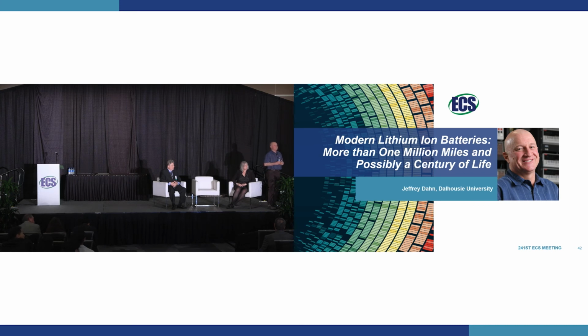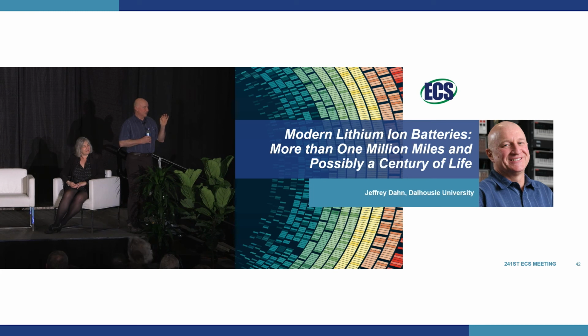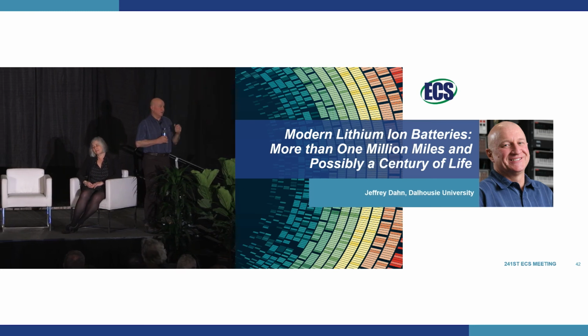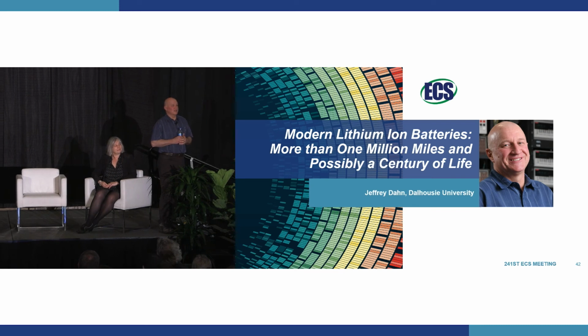I say, how about single crystal? Have you tried the single crystal lithium iron phosphate? Well, what is single crystal lithium iron phosphate? I mean, what we use is lithium iron phosphate that are very small nanoparticles, 100, 200 nanometers, and they're all single crystals at that size. So I guess we are trying it, but they're small. NMC is more than a micrometer, is that right? Oh, heck. There's a lot of troubles using large-sized lithium iron phosphate. The lithium ion diffusion constant within lithium iron phosphate is very, very slow. So a big primary particle of lithium iron phosphate would have very terrible rate capability. Thank you.